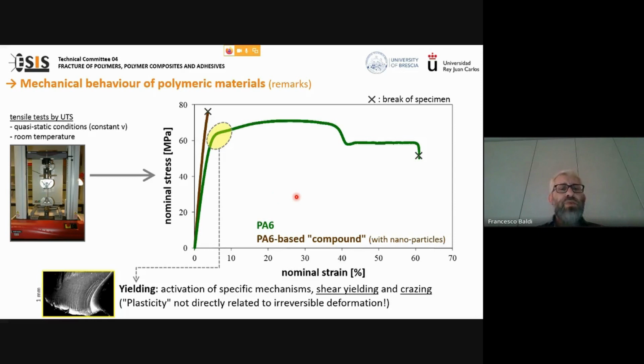Now, the difference between them is clear. On one side, we have the compound that exhibits a brittle behavior characterized by a strain at break that is around 4%. Whereas if I consider the PA6, I can observe an elongation at break that is around 60%, that is reached after an extended deformation region that is governed by specific deformation mechanisms, which activate at yielding here in the area highlighted in yellow.